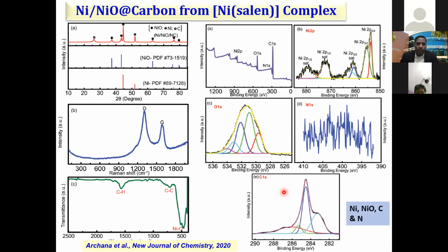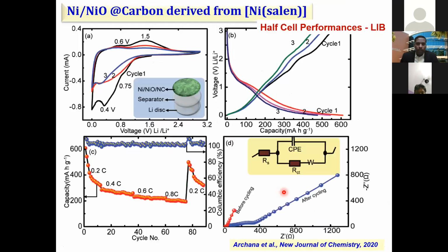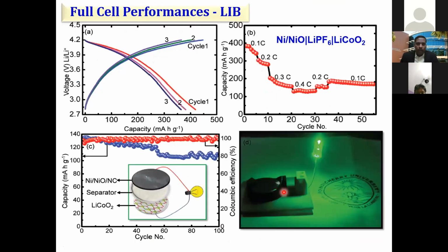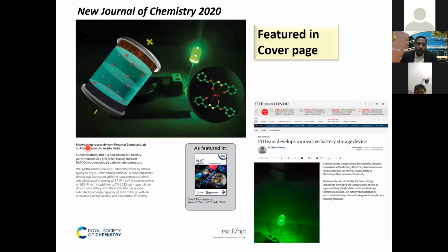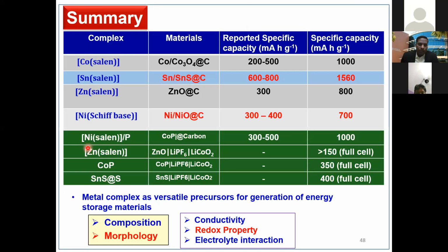So in the same way, we have also made nickel oxide on the carbon matrix as an alternative anode. And this is the half-cell performance, and this is the full cell performance. So nickel oxide versus lithium cobalt oxide can be used as an alternative anode, and the discharge capacity is as high as 700 mAh/g. It was recently covered as a cover feature in the New Journal of Chemistry. To summarize, I think I'm quite within the time.